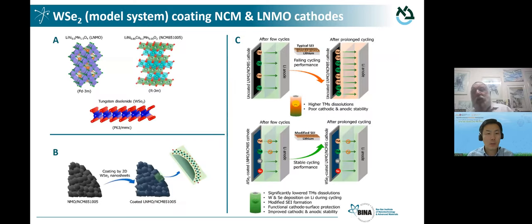The next issue relates to high voltage lithium nickel manganese oxide spinel, and here we use tungsten selenide. People will say tungsten selenide is an exotic material, not practical to use, but this is just a model system, and we have many layered compounds now which are cheap and relevant, and papers are in preparation. But the idea is that here we show an important concept. We use layered material that can adsorb to the surface, and we did experiments with nickel-rich material, 85%, and also with this lithium nickel manganese oxide spinel. And we have adsorption of this tungsten selenide on the surface of the cathode. So we form a buffer zone, and I'll tell you in a minute why it goes for.